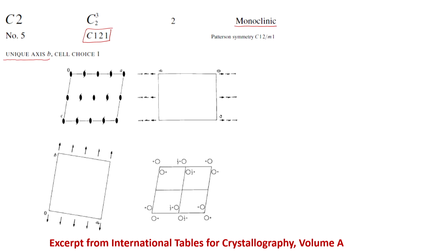If you look at this diagram, we have a base as the parallelogram here, or rather it is an AC face, and the B axis is perpendicular to the AC face, where the two-fold rotational symmetry is. So, there is a two-fold out here, and then the two-folds get populated to the corners, and you also get them at the edge centers.